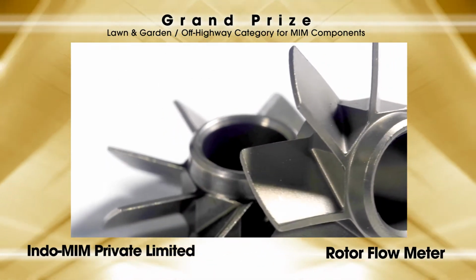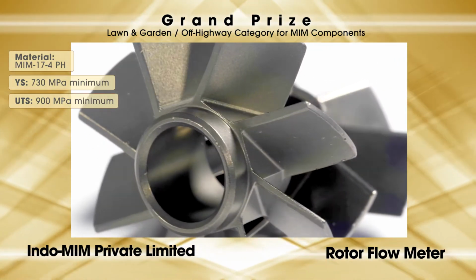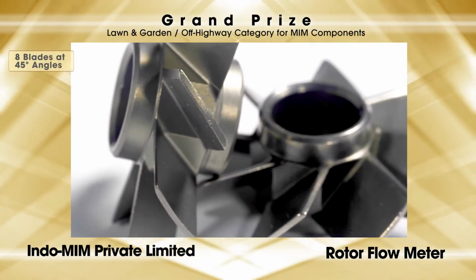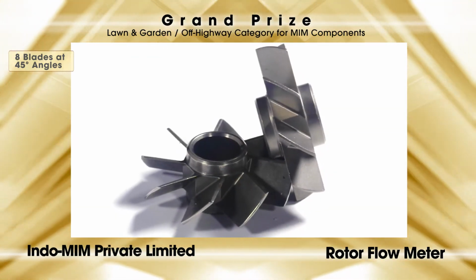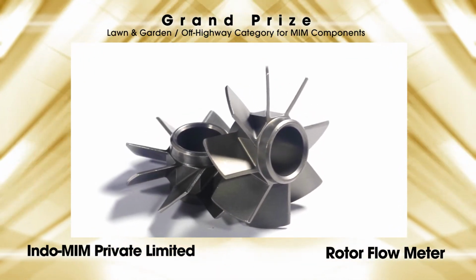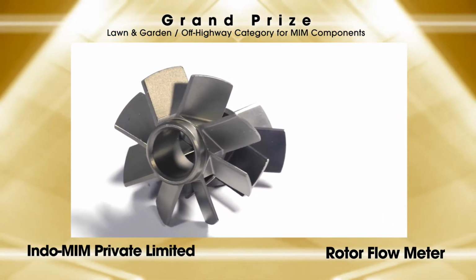The component is made from MIM-17-4 PH stainless steel, has a yield strength of 730 megapascals and an ultimate tensile strength of 900 megapascals. It has 8 blades angled at 45 degrees around the circumference and a sectional thickness of 0.64 millimeters. A single cavity mold is used with 4 side cores. To ensure the side cores had reasonable strength, the 8 blades are formed using 4 side cores, with each side core making 1 full blade and halves of 2 other blades.